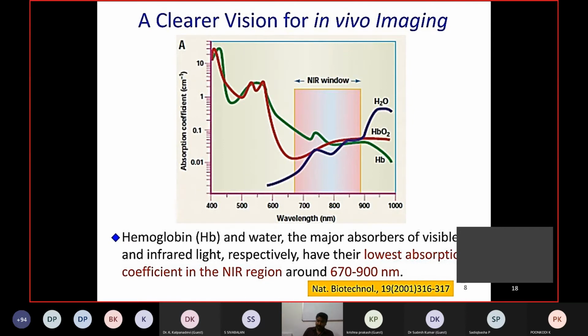That NIR2 window, of course, is very interesting, and the absorption by the natural tissues is low. Absorption by the material is larger, and that will not cause harmful effects to the tissues either, because the wavelength is longer and the energy is lower. But the problem is you have to design NIR2 materials. These gold nanoparticles absorb commonly in the NIR1 window. Maybe some gold nanomaterials may be made to absorb in the range 1000 and above, but it's difficult. The preparation procedure is difficult. The size is also not in this suitable range. So we look for newer materials.